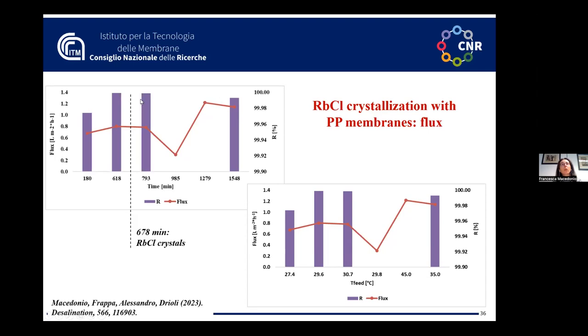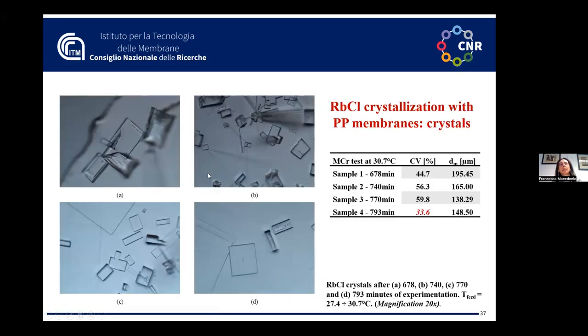In all the tests, what we can see was that in any case, the rejection was very high. And here are some pictures of the rubidium chloride crystals as achieved during the test with the polypropylene membrane. What we can see is that the crystals were very good, with a very low coefficient of variation, 33%, which is good if we consider a process that can be scaled up. The coefficient of variation is the parameter which gives an indication of the distribution of the crystal size around the average size, and a value of 33 is really good.